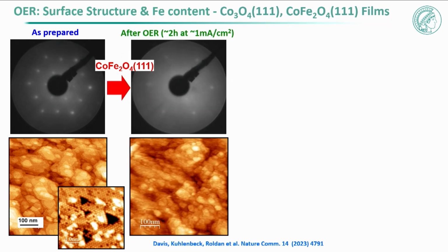So after the reaction, you can see that the material changes. You see more roughness. In these images that are low energy electron diffraction images, you see already that something happens. So this disorder of the surface indicates that we have the formation of this thin oxyhydroxide layer. And by now we can measure and we know that this is less than 1 nanometer.